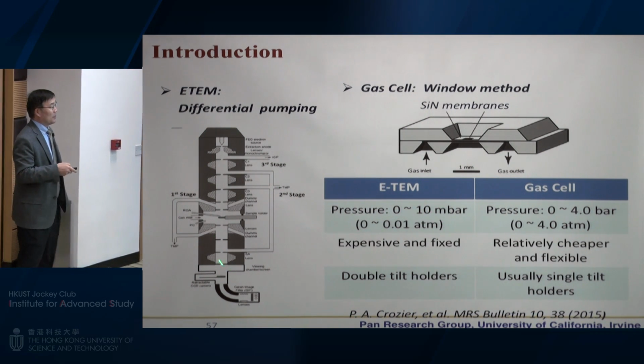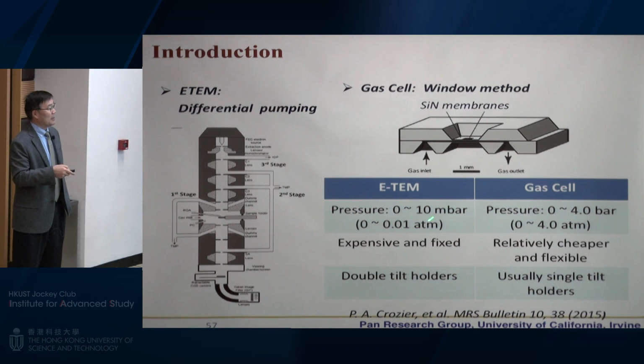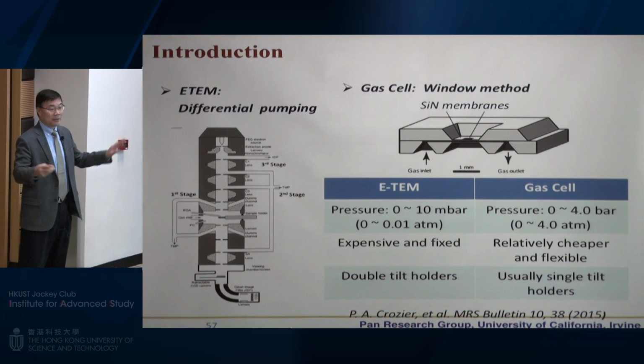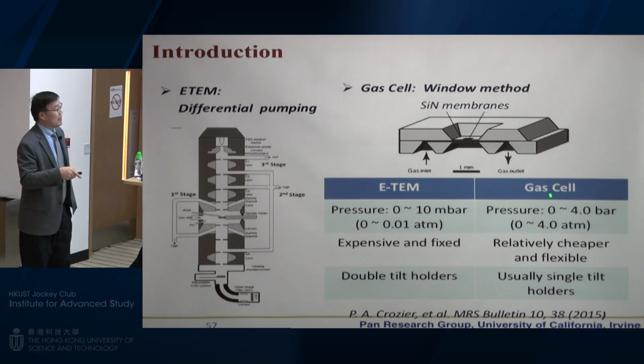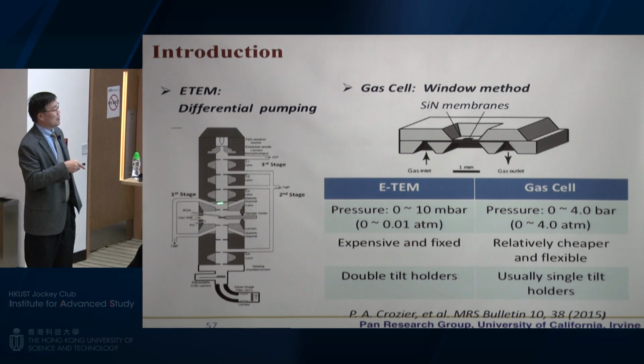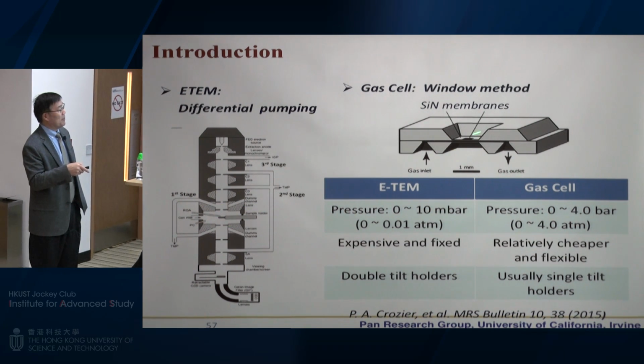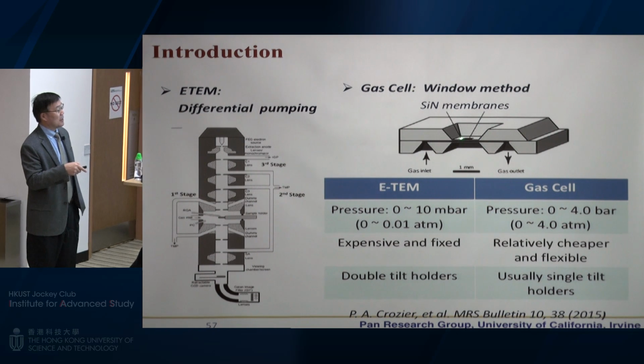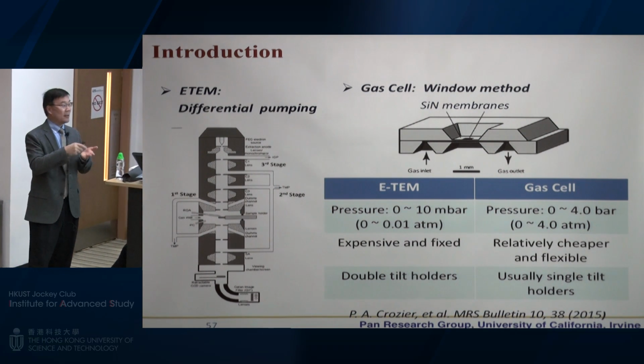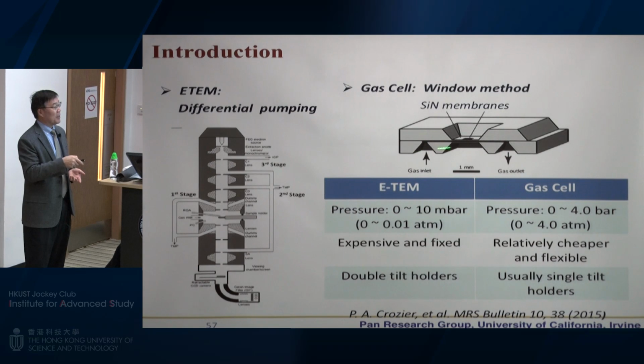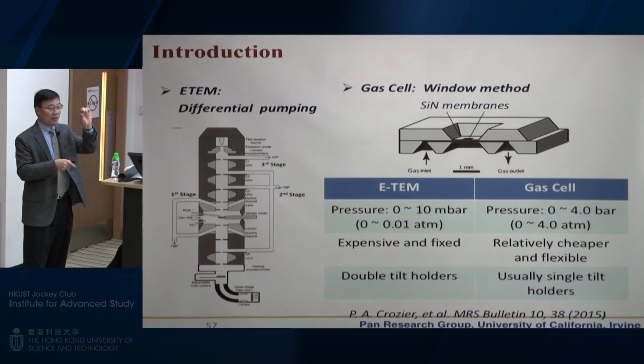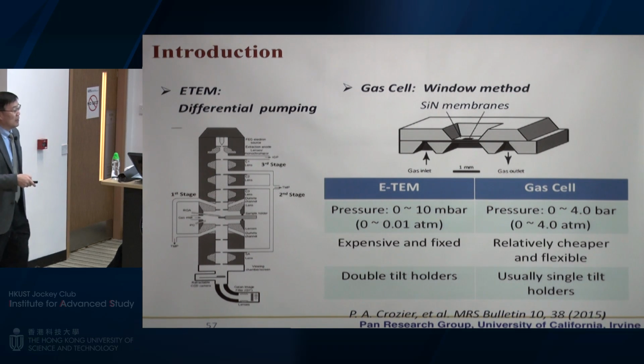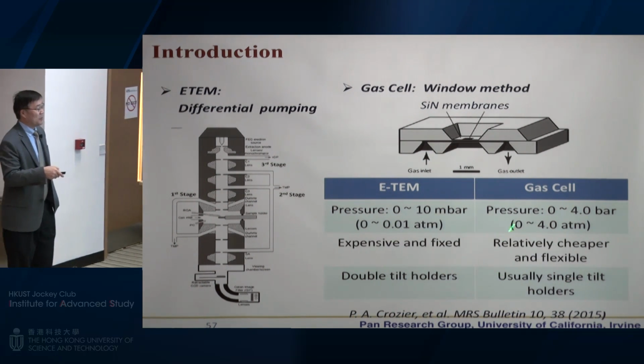Okay, so the simple reason is that if you increase pressure further, then the differential pumping will not be efficient, then the microscope will not work. Another way is we do not use the special built microscope. We just use a regular TEM, but build a holder which has a two-piece of membrane so that the gas can go in and pump out, and then in real time, just through very small volume, between two membranes. So this is the method that Protochips developed.